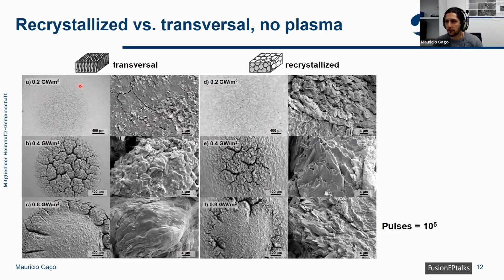So we can see that first, with the lower power loads here, there is almost no cracking, maybe some cracking can be seen, a low surface modification. Also, no tungsten fuzz is formed, because tungsten fuzz forms only when plasma is applied. So here it was not really expected. And then the cracking network begins to form once we increase the power load. And when we increase it even more, then actually something interesting happens, that there are no cracks in the center of the laser spot, but only on the outside, which was not observed with 0.4 gigawatts per square meter.